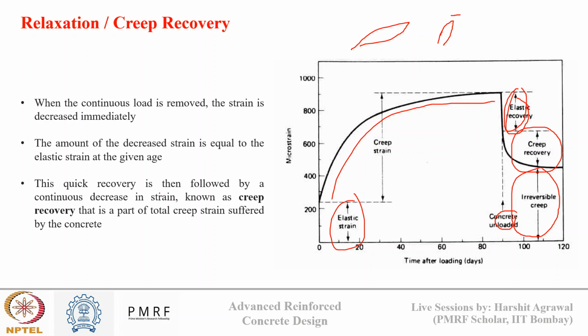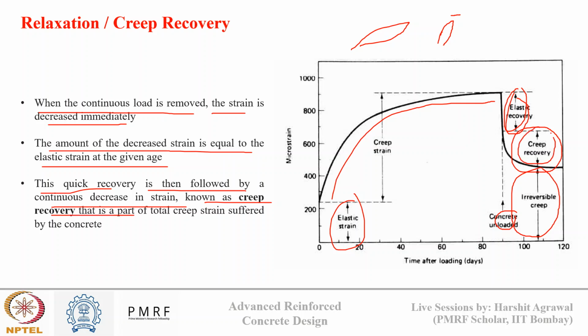If you see here in the text also, the same thing is mentioned. When continuous load is removed, the strain decreases immediately. The amount of decreased strain is equal to the elastic strain at the given age. This quick recovery is followed by a continuous decrease in strain, which is known as creep recovery. This is a part of the total creep strain suffered by the concrete. Out of this total strain, a small portion is recovered and the remaining portion is irreversible.